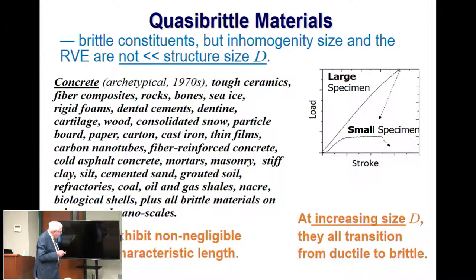So these are materials which exhibit non-negligible material characteristic lengths, which is basically the length of the fracture process zone. What is interesting is that as the size gets bigger and bigger compared to the material characteristic length, they transition from ductile to brittle behavior. And the load-deflection diagram changes, small, large, you have a size effect and all that. All right.